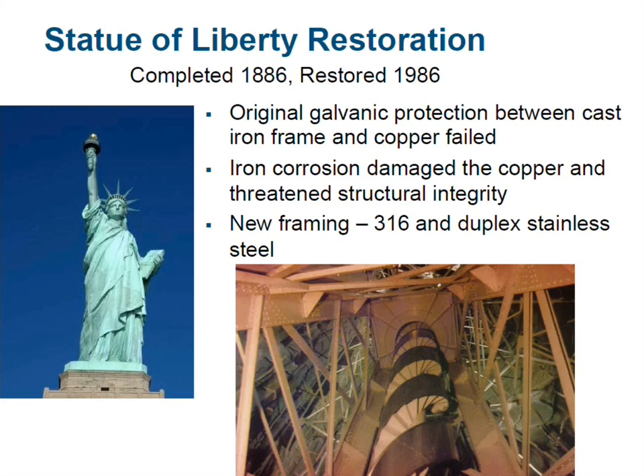One example of that was the Statue of Liberty restoration. When you put large sections of copper in direct contact with cast iron in a structure where moisture is going to infiltrate, you're asking for galvanic corrosion problems. The designers did understand that, provided for separation, which went away over time. And then there were additional efforts to separate the metals, but there was iron corrosion, which expanded and damaged the copper, and in the early 1980s, they started looking for solutions. The secondary framing is a duplex stainless steel, and then the bars that are in direct contact with the copper are 316, which has the same coefficient of thermal expansion as the copper, unlike the original cast iron.